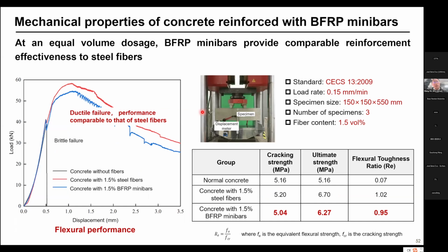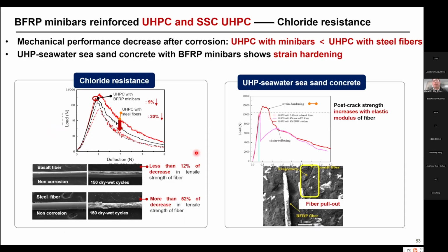So we did the experiment and it shows that by using the macro fibers, and sometimes a hybrid of macro and micro, we can achieve behavior similar to that of steel fibers. The mechanical property is similar to steel fibers, but from the view of durability, it shows a much higher resistance to corrosion.